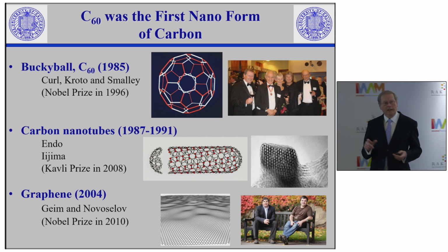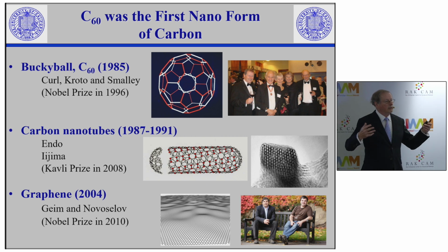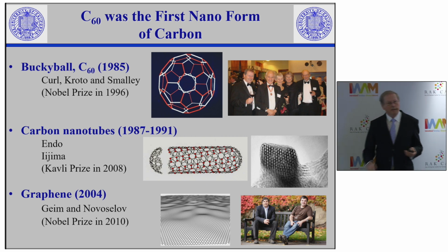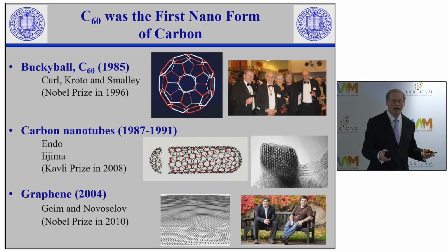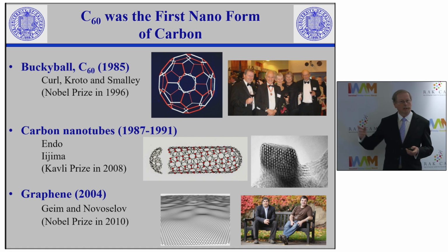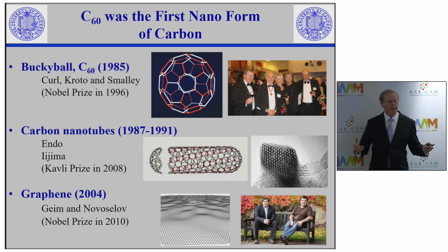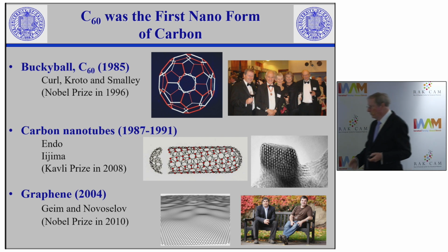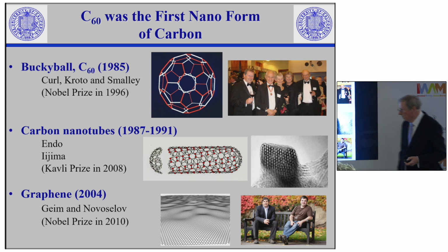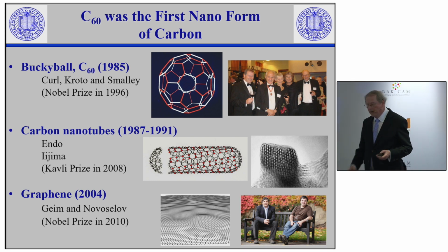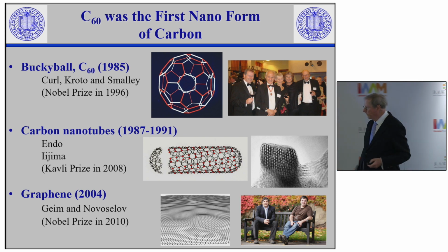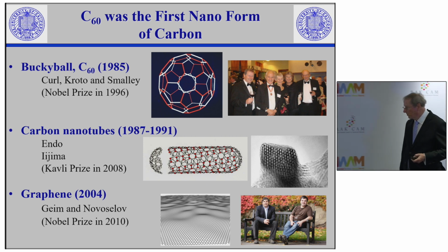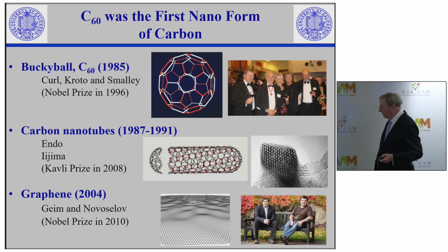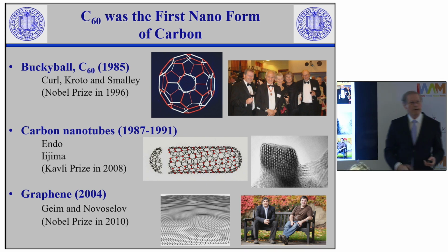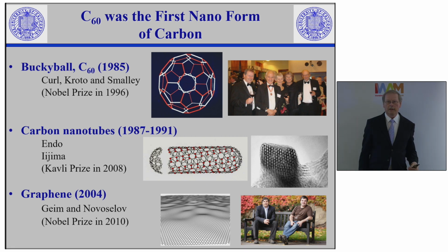But the irony is that even though the Buckyball made a huge splash, in a way it didn't have any commercial impact, or very little. What it did do was spawn a lot of interest in other nanoforms of carbon. If you can make C60 in balls, could you make tubes? Endo and Iijima in Japan both made carbon nanotubes, which was recognized with the Kavli Prize for Iijima about 15 years ago. These are basically like the Buckyball: if you take a Buckyball, cut it in half, and then roll up one of Andre's graphene sheets and cap the ends, you've got a carbon nanotube.